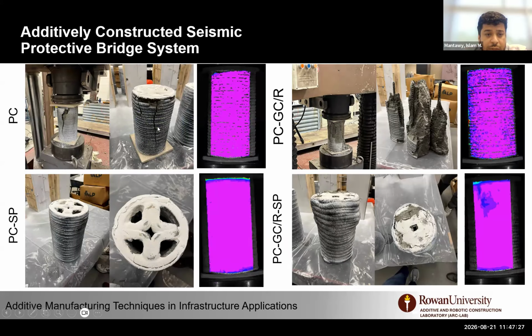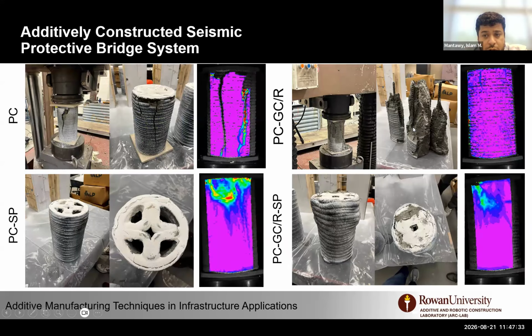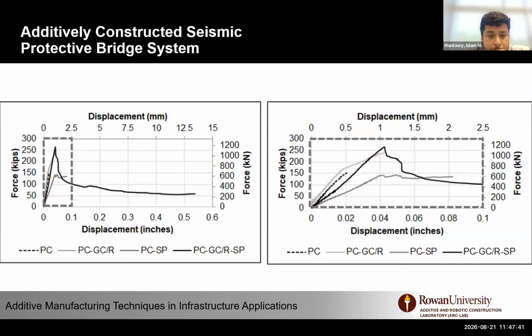So basically, as expected, the 3D printed alone has brittle failure, similarly to the reinforced one, because it doesn't have confinement, and the other ones that have confinement were able to undergo post-peak ductility. Here are the results for those 4 different columns, and you can see here we actually increase the capacity as we add those components, either the spray or the reinforcement, but also we get post-peak ductility.